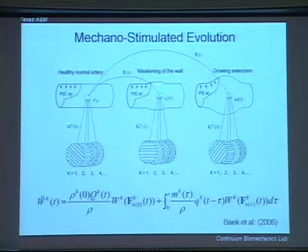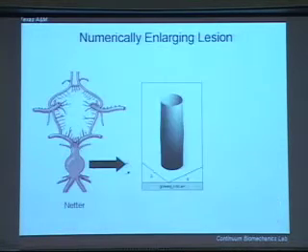That degradation will, of course, weaken the wall locally, which will cause the artery to bulge out slightly under the same pressure. Because of this slight bulge, we have actually changed dramatically the stress in this region. And we think that the stress seen by the cells will actually affect the rate at which the cells produce or remove matrix. And so now our goal is to evolve this aneurysm numerically with different hypotheses and then compare these competing hypotheses.